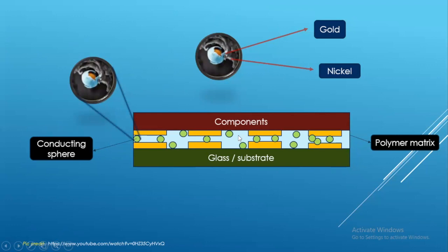Yes, sir. So what is the size of these yellow strips or yellow parts? Generally, these yellow parts, which are gold thin films on our glass slides, are 10 micron to 60 micron maximum. In our mobile phones and laptops, they have this dimension. In calculators or displays without that much resolution, they may be 100 microns or 200 microns. Okay. And these nanoparticles are in nanometers.